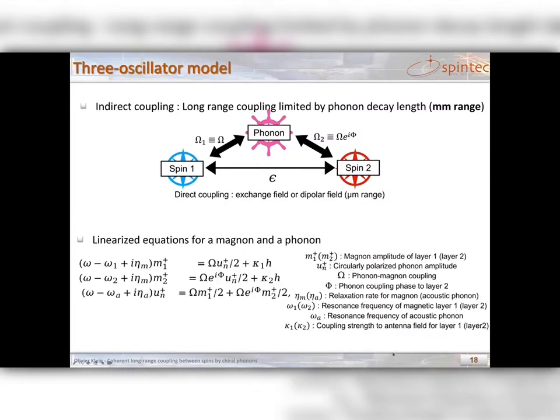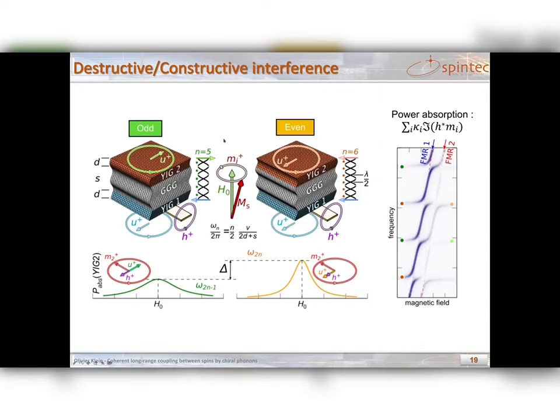So our two oscillator model can now be extended to a three oscillator model by just adding one new line, where the magnetic layer is driven by the phonon-magnon coupling with its phase also set by the antenna. So we have added this line. So what do we expect now? The odd phonon drives the top layer with opposite phase to the antenna, as shown here. Therefore, they are competing and the power absorption is reduced. This is because M2 is lagging in phase by 90 degrees compared to the acoustic field.